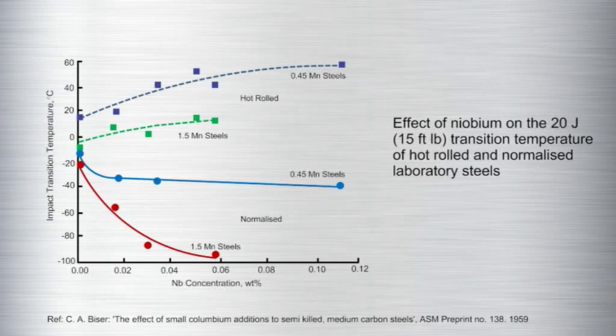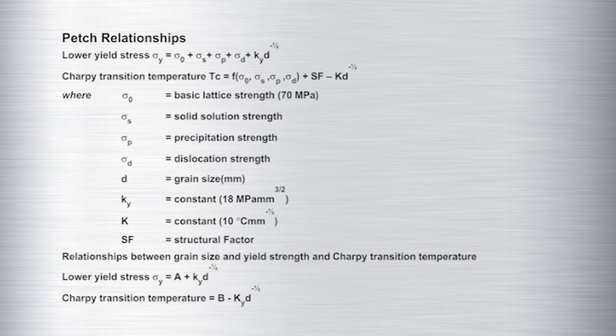Biser, from Union Carbide, also had some research done in 1959, in which he suggested that although niobium caused grain refinement, it also formed a brittle grain boundary carbide, which caused poor fracture toughness problems. There were other explanations floated around about that time. One was solid solution hardening by niobium, and one was that niobium and carbon formed molecules. But none of these explanations told the whole story, and none of them satisfactorily explained the structural properties of niobium-treated steel. The credit must go to Jack Woodhead for utilising, for the first time, structure-property relationships to study the effect of niobium. These were based on the Petch equations, which related grain size to both strength and fracture toughness. And this was the first time that these equations had been used in this way.